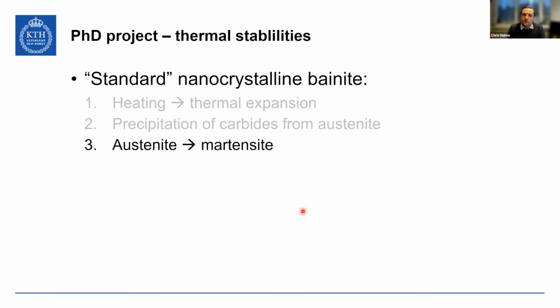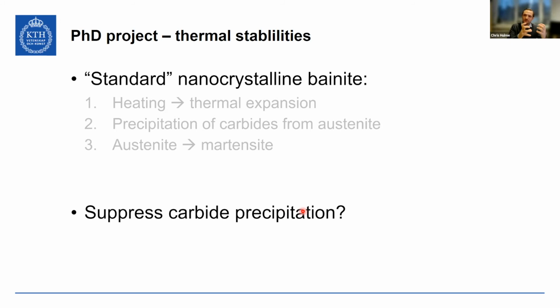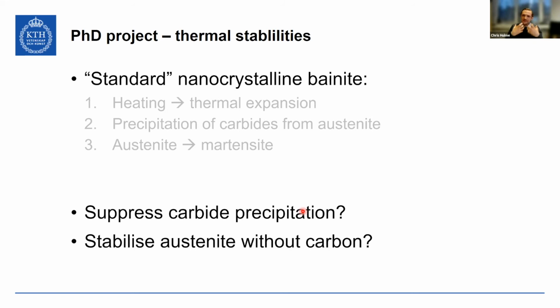And that then gave me two ideas based on that literature knowledge. Could we suppress carbide precipitation completely? That's what led to the principle of alloy 8, with the high silicon and aluminium contents, which were as high as I dared make them without forming lots of dross. Or could we stabilize the austenite without carbon? And that's where the alloy 9 concept comes in, with lots of nickel and cobalt.